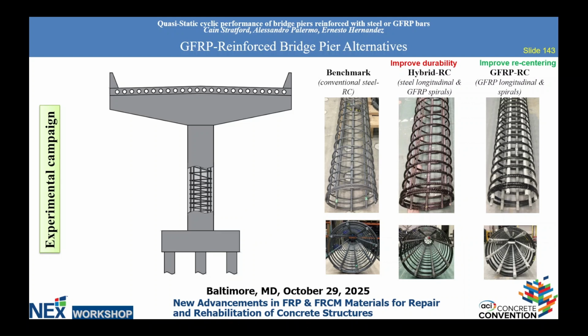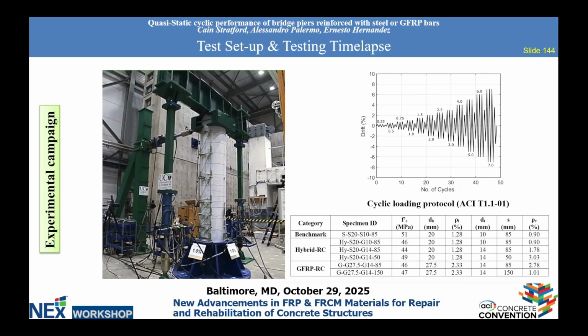Then the hybrid that we did, which is different from what I was referring to before, in this particular project we looked at using spirals with GFRP, but with steel reinforcement, and then we wanted to do a full GFRP column. So solution number 2 is more to improve durability, because corrosion usually attacks the stirrups first. Solution number 3 was to look at a full recentering system, because what we found is that, very important for earthquake performance, is the ability of the structure to recenter and go back to the original position. We tested 6 specimens for this campaign.